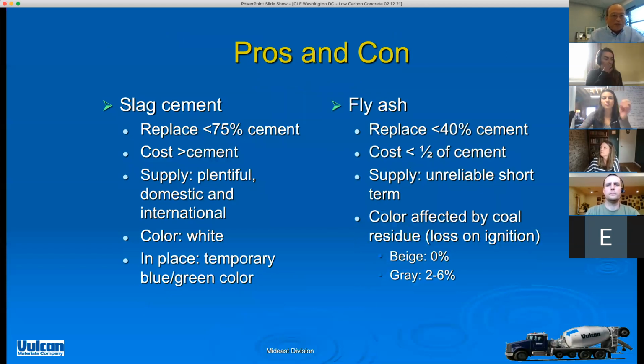So the pros and cons of the two different materials. Looking at slag cement on the left, it replaces up to 75% cement. That's the typical usage. The high slag content is typically used in mass concrete, where we're trying to keep the temperature of the concrete within a certain specification limit. Cement is the heat generator, and therefore avoiding cement makes perfect sense. And voila, it's good for generating very low carbon concrete as well.